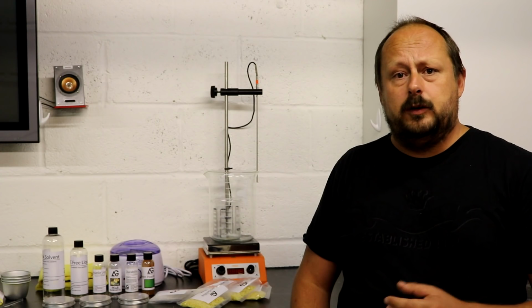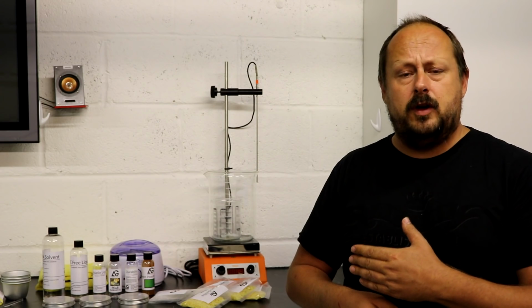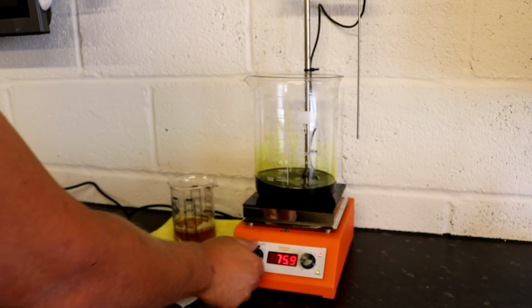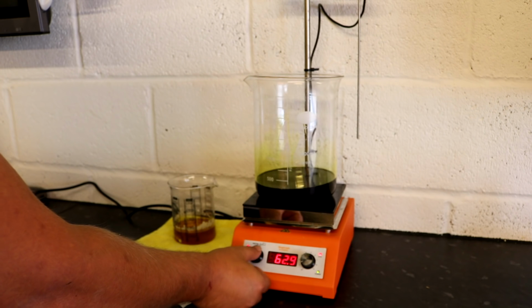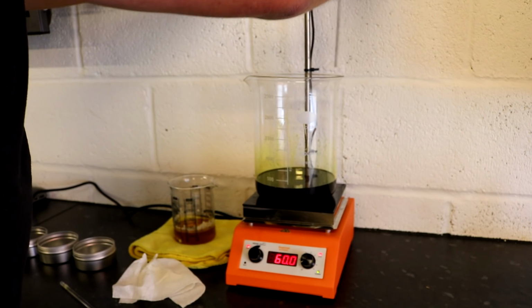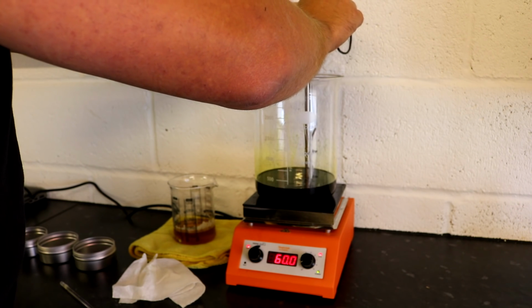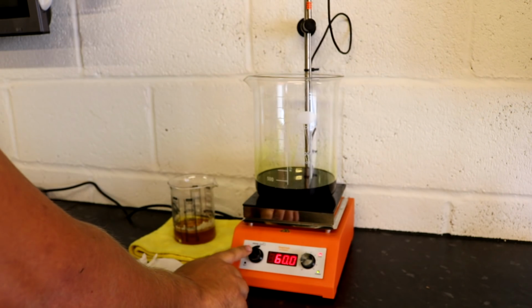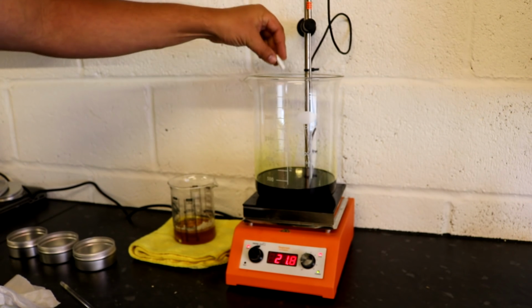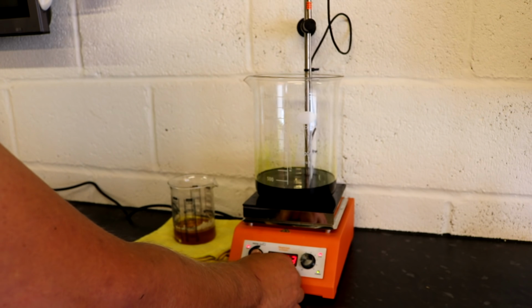When it starts getting below 60, it will start solidifying, and you'll see the top and around the edges start to solidify, okay? So we want to ideally get our other liquid beaker up to temperature before that wax is cooled below 60. So we put our liquid blend of solvents and all those special carriers and polymers on there, and we heat this up to 60 degrees. So I can set the temperature on this to 60 and watch it slowly rise. If you're doing this bit in the electric wax tub, or on the saucepan, be very careful to not overheat these polymers, okay? They'll go blobby and stringy if they're anything like the ones that I've used before. So do not overheat these. It says heat them up to 60 degrees, okay?